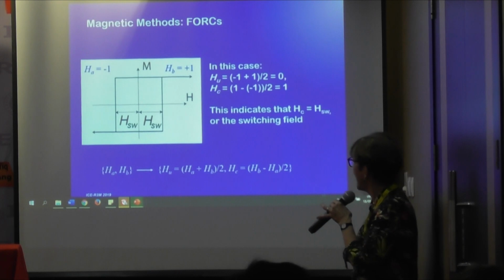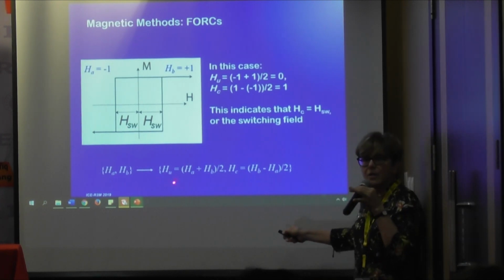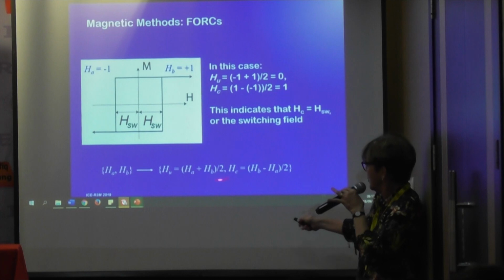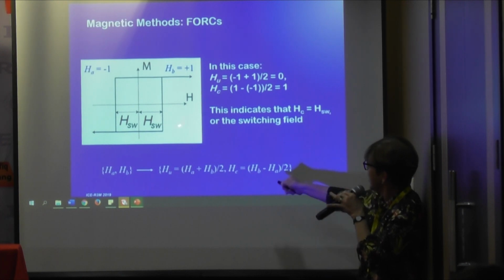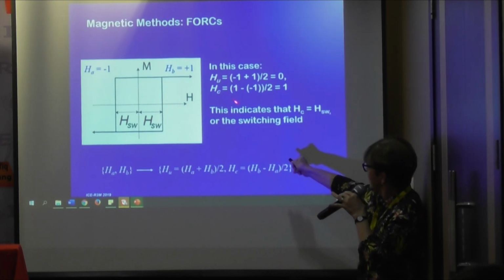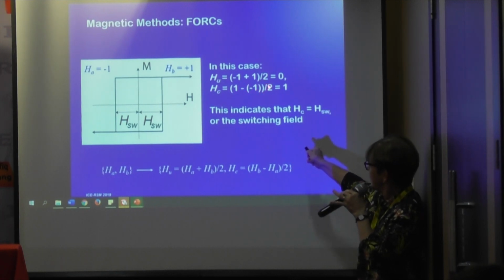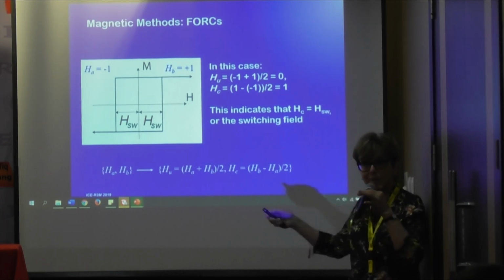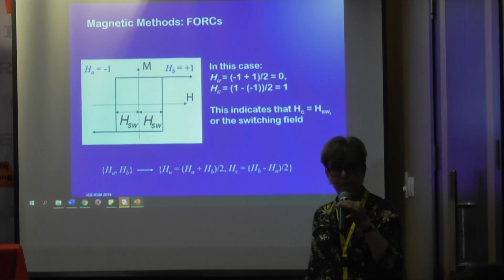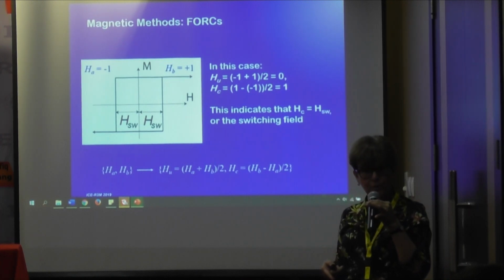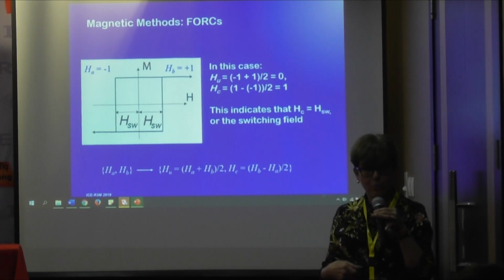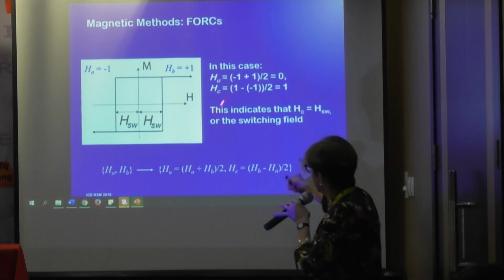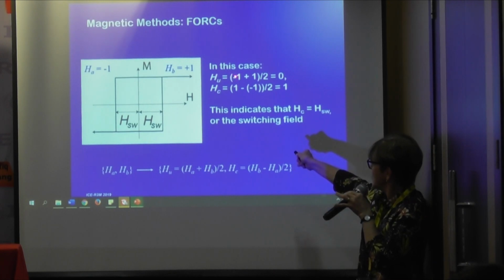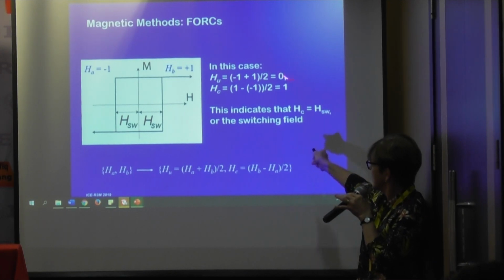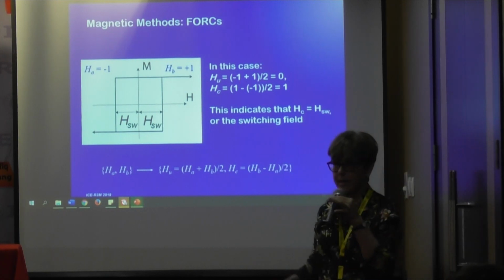To get the average coercivity is very simple. It's just my +1 here minus my -1, divided by 2, so my coercivity of that material is 1. Now if I want to know the interaction field, are these particles interacting with one another? I'm going to use HA plus HB divided by 2. So I have -1 plus 1, which gives me 0, so I have no interaction in this case.